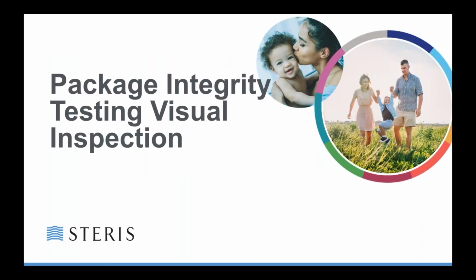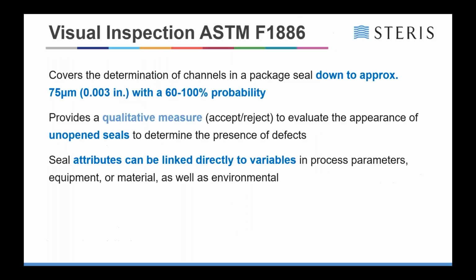If we look at the visual inspection, this is done to a standard called ASTM F1886. Currently this standard only looks at the seals of the actual pouch or tray, as the case may be. But you can detect a defect down to approximately 75 microns with a 60 to 100% probability. Again, it's a qualitative measure, and as I said, it's on the unopened seals to determine the presence of defects there.